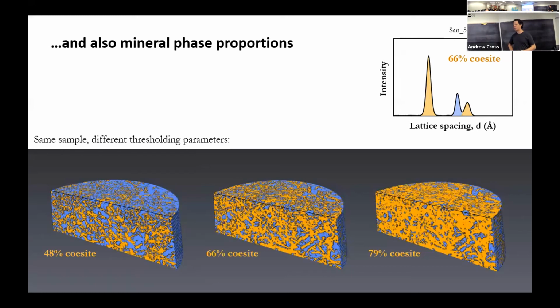These are what the CT scans look like. And we've actually got quite a bit of wiggle room in terms of where you pick the threshold for separating out those two phases. So this is a conservative lower bound, and then a conservative upper bound on the amount of Coesite. So Coesite is the orange phase here, and quartz is in blue. And then our middle, happy medium estimate gives conveniently 66% Coesite, which perfectly matches our spectrum here.